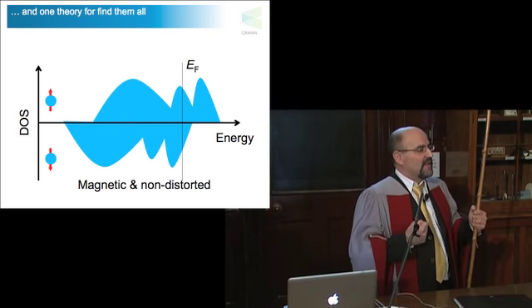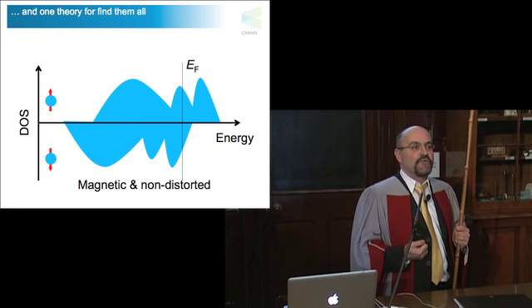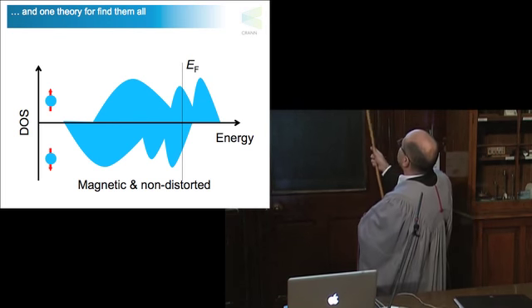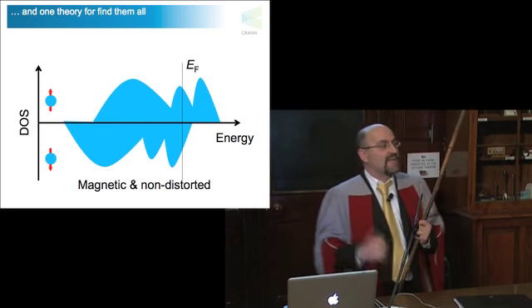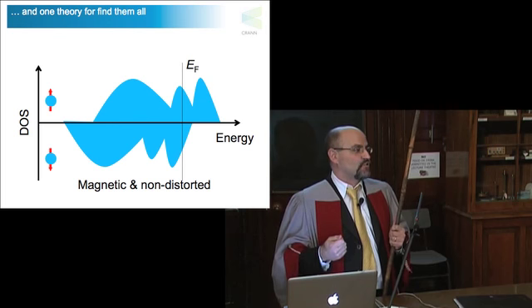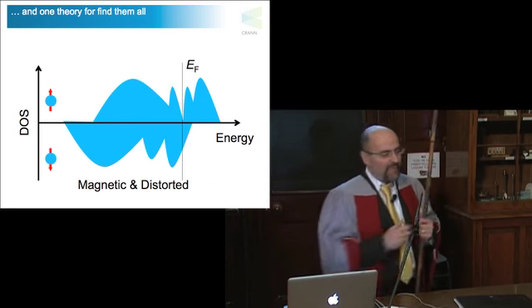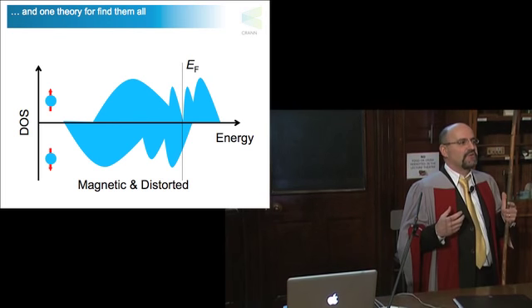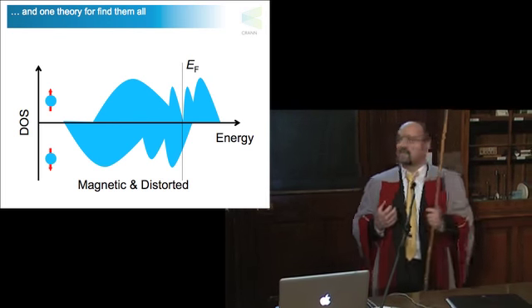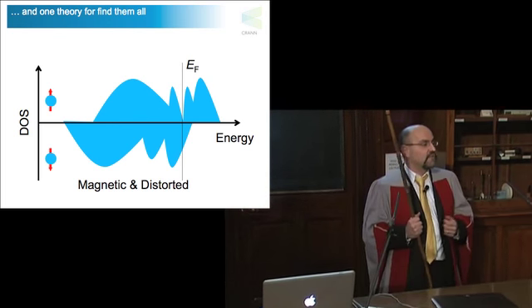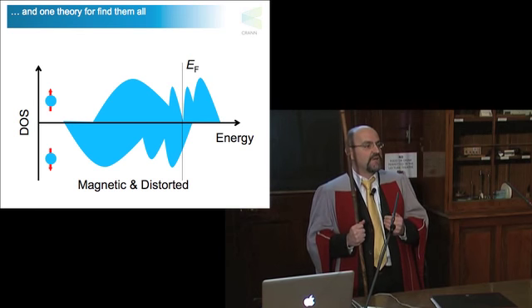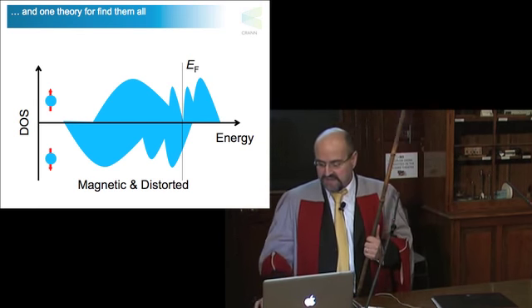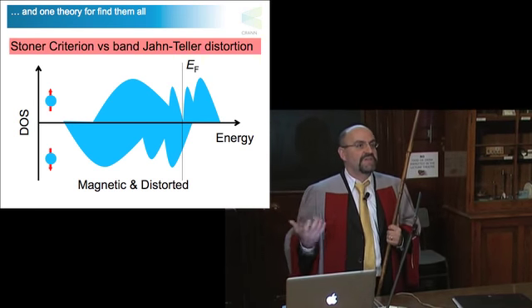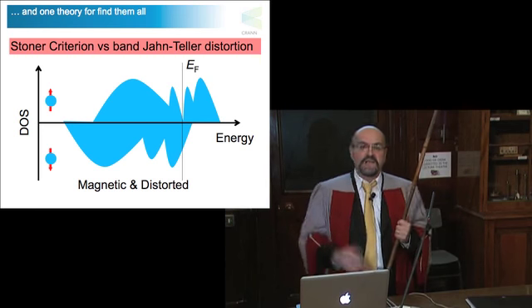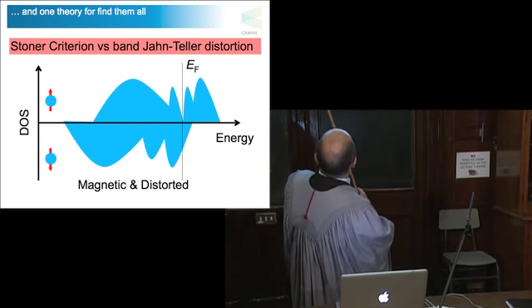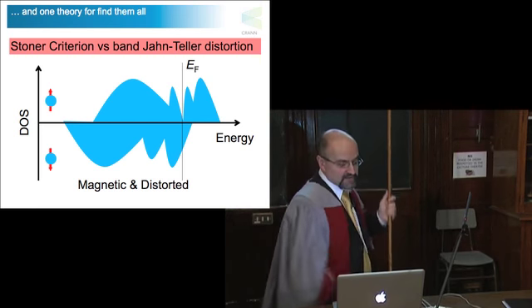But now, when you do this, because the density is so peculiar, some of them still end up with a peak at the Fermi level. And then there is another mechanism that can kick in, which is a structural distortion. And the structural distortion then opens up a gap. You have to have some other thing going right for this to happen, but it's what we found in the database. And the structural distortion gives you this new density of states, which is the one that lowers the energy. So what we found by looking in the database is essentially that the emergence of this particular class of material is due to two competing factors that are technically called the Stoner criterion and the band Jahn-Teller distortion mechanism.